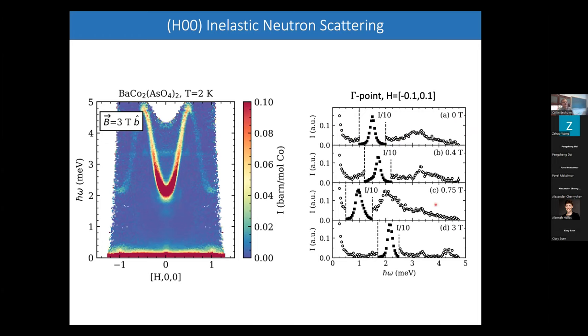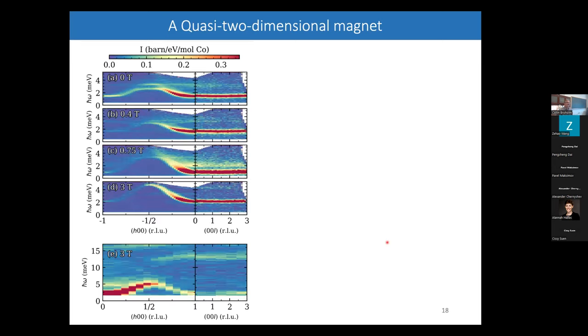And so as I come up to 0.75 Tesla, which is a little bit beyond the point where you suppress the magnetic order, we have a very strong peak very close to the 2-magnon point. So twice this energy is where you tend to see this peak. But then when I drive up to 3 Tesla, then I've significantly suppressed these 2-magnon contributions, and most of the intensity lies in the coherent mode. So there certainly is interesting continuum scattering in this system. This may relate to its potential for spin liquid type physics.